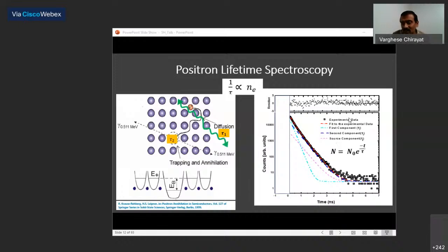And that is what you see here. When you deconvolute your spectra, in this specific case, it can be deconvoluted into 2 lifetimes. I have shown the first component by a light cyan color, and the second component by dark blue color, right? So those 2 components are telling you that in this specific material where I have measured the positron lifetime, some of the positrons are annihilating at a place where the electron density is small, and some are also annihilating at another location where the electron density is large.